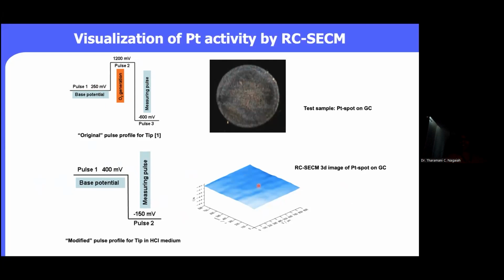Surprisingly, you can see that this is a 3D image. We do not see any hump in this case with respect to the platinum spot. What we did is that we took the sample out and checked it under the microscope, and we saw that there are a lot of holes on the electrode surface. And after close observation, you can see that the distance between these two spots is almost 50 micrometer, and the diameter of each spot is about 25 micrometer. That means we are moving the electrode at every 50 micrometer grid point, and also the diameter of a platinum microelectrode is 25 micrometer.